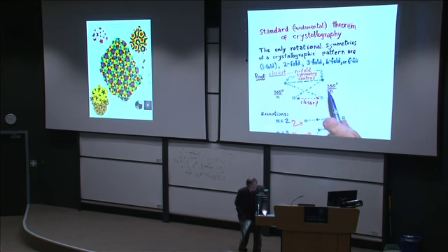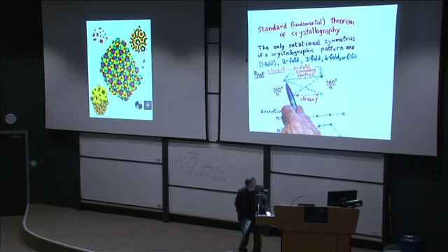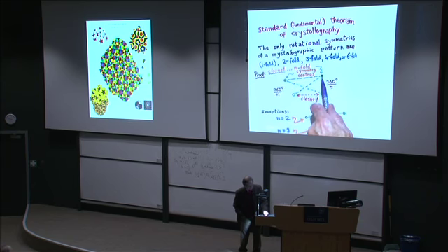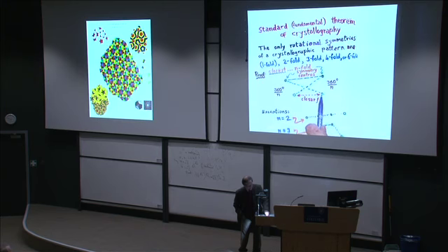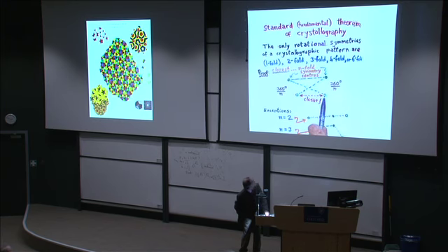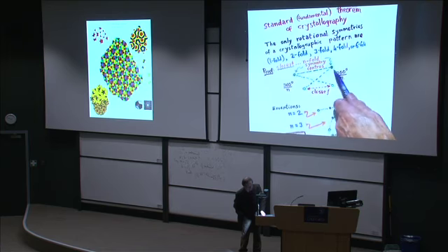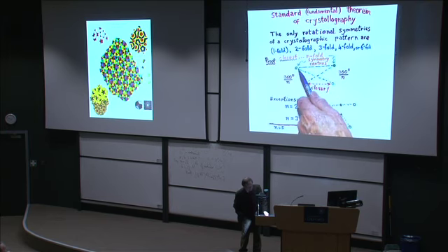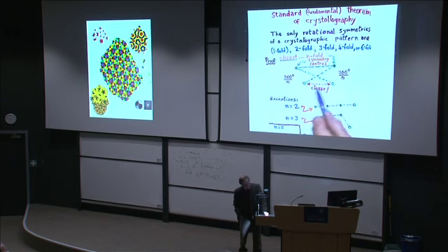Now I rotate this one about that one by the symmetry, 360 over n, and since the pattern is the same when you rotate through that, that also must be an n-fold symmetry point. Then I rotate the other one in the opposite direction, so that one must also be an n-fold symmetry point, and you see those are closer together, which contradicts these two being as close as possible.